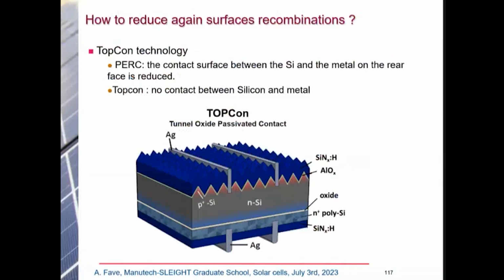So there is no recombination because there is no contact between silicon and metal. There are no defects at this interface. But we need a very, very thin oxide, only a few nanometers. Okay? So there are different kinds of TOPCon solar cell. This is the most standard one.